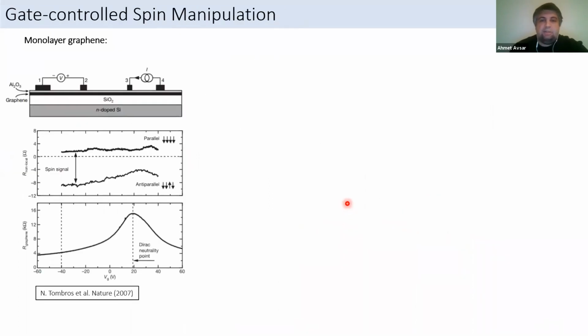And in this heterostructure device, you could do something more. We did some PN junctions, etc. But another thing we could do is controlling the spin signal with the gate voltage. In monolayer graphene, it's a semi-metal. It's a metal basically, and even though it's monolayer, the change you can have in the resistivity of the material with the gate voltage is very small. It's also the same for the non-local signal. With the gate voltage, you can only change the spin signal very little. At least you cannot make it on and off, which you would expect in a semiconducting material.